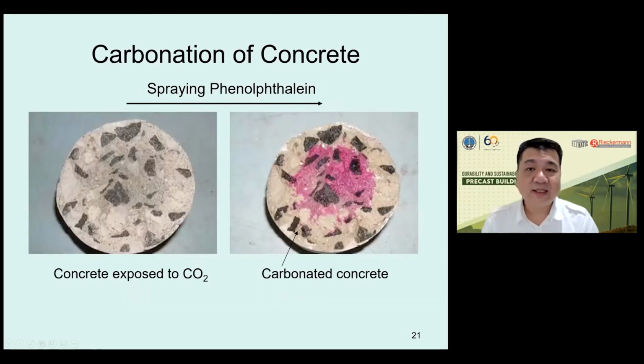Now, we can detect the carbonation of concrete using phenolphthalein solution. When we use phenolphthalein solution, we spray it on the concrete. When the concrete changes color to pink, it shows that there is some calcium hydroxide in the concrete, and this part is still relatively high pH, while the outside is already lower pH. So this is the carbonation.